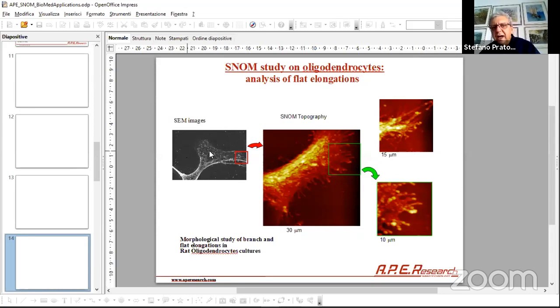By comparison, I put here a SEM image, scanning electron microscope image. This is the part of the cell that we want to study. With a scanning electron microscope image, you are not able to see anything of this. Why? Because to make this SEM image, you have to evaporate on top of your cell some gold or carbon to make it conductive, because the electron microscope requires that the sample is conductive. You agree?